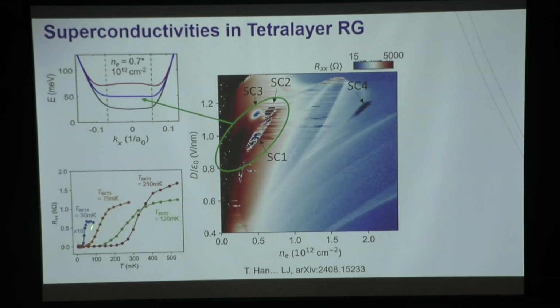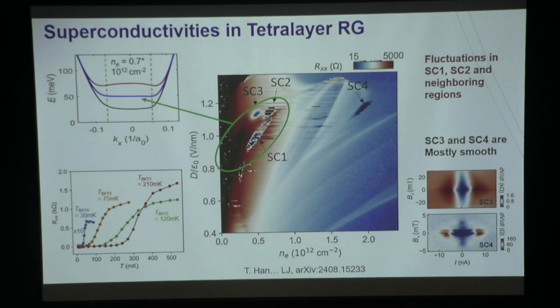And the Tc of this superconductivity, none of them is high, okay? We're all talking about below 300 millikelvin through the BKT fitting. However, you probably already noticed some very bizarre looking features: there's a lot of fluctuations in SC1, SC2, and then the neighboring area here. Well, SC3 and SC4 are mostly homogeneous. As far as we can tell, SC3 and SC4 just look normal, that you apply a small out-of-plane magnetic field, you can easily kill these two superconductors.